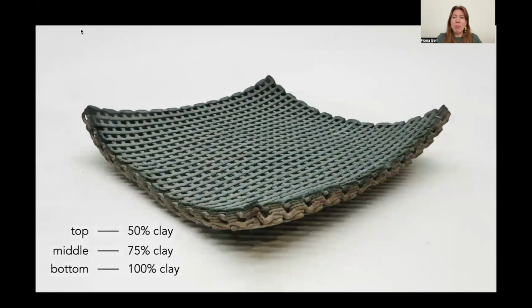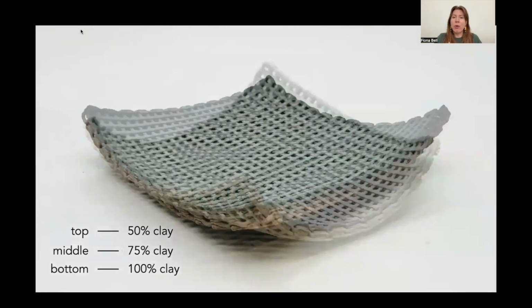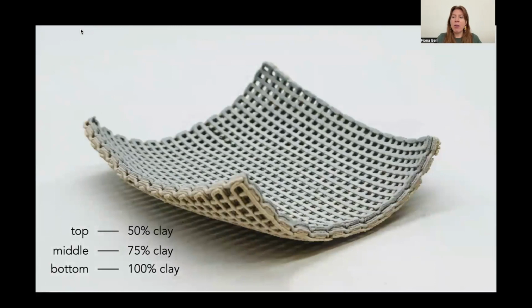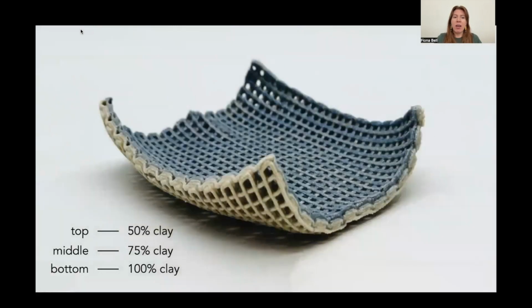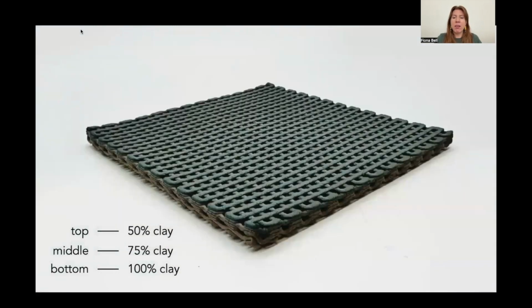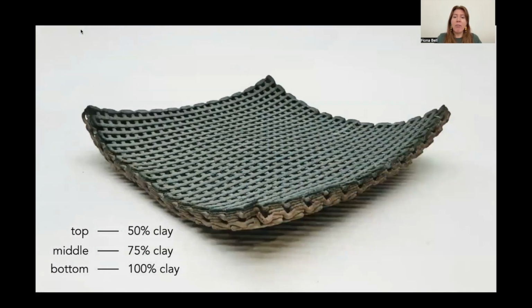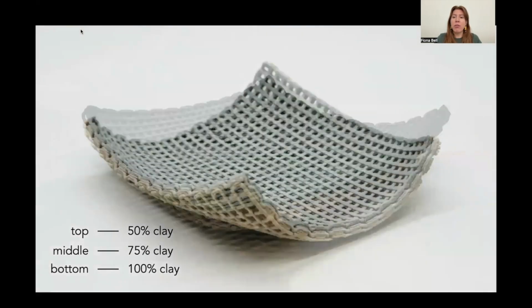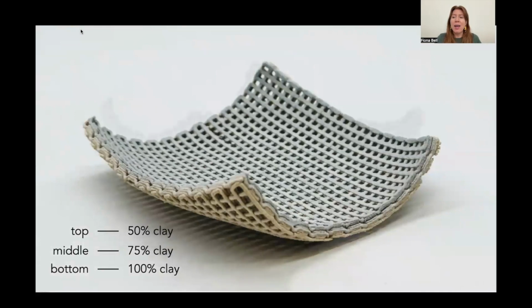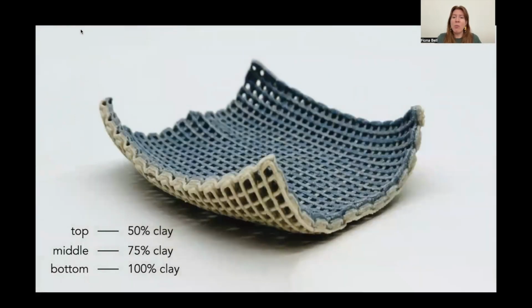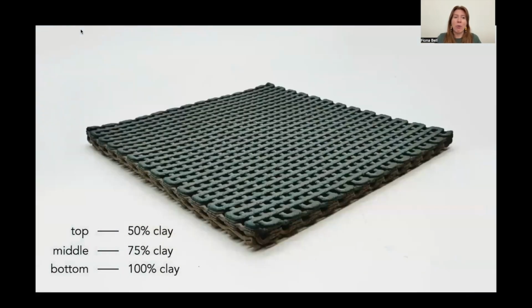We intentionally printed this plate with 100% clay at the bottom, 75% clay in the middle, and 50% clay on the top. As the 50% clay shrinks more than the 100% clay, it pulls the edges upwards and inwards into this new bowl-like form.